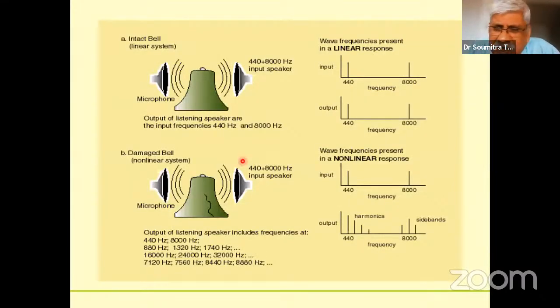The concept of nonlinear ultrasonic is actually very simple. If you use certain frequencies and impose that on a structure, sonic frequencies, let's say 440 and 8000 hertz, then that structure resonates, like a bell resonates. And the resonated output from that structure can be again captured, received, and it will be the same as the input. So the output will be the same as the input. But if that structure contains defects, damages, for example, if there's a crack in the structure, then the output will have additional harmonics.